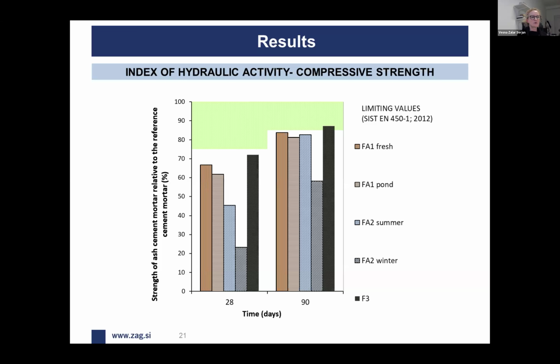systems are not completely the same, because you are exchanging 20%, 25% of fly ash with the cement in order to prepare a mortar, standard mortar bars. But anyhow, the results gave us some clue about how the material could react if we used water and put an additional activator inside, such as cement or pure lime, in order to increase the pH and increase the solubility of the amorphous phase. We can see that